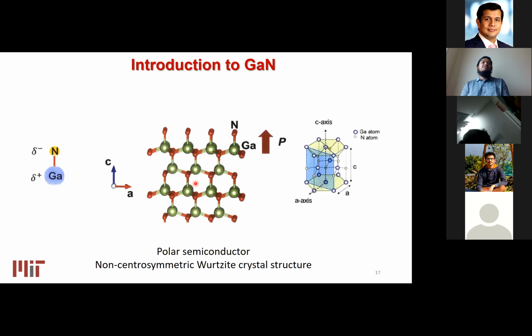To introduce gallium nitride, it's a compound semiconductor, and it's called a polar semiconductor, which means the crystal structure of gallium nitride is not symmetric. If you look at the unit cell of gallium nitride, there is a built-in charge dipole. And this is also a piezoelectric material. Unlike silicon, it's not a cubic structure, it's a hexagonal structure, as we can see from the top view image here. It's a so-called wurtzite lattice, where we have gallium and nitrogen atoms in the structure. This piezoelectricity, or this polar semiconductor nature, gives some unique advantages that no other semiconductor material actually possesses.